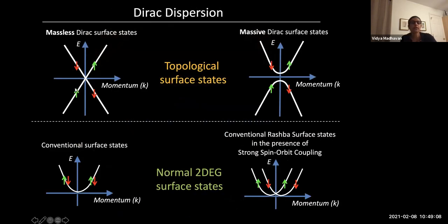So just to show you why a topological insulator is interesting, this is the band structure of the two-dimensional surface state of a topological insulator. And this is the Rashba split state that I was talking about earlier. The difference between a topological insulator and a Rashba split band is that at any given energy for a topological insulator, you have only one band crossing that energy, whereas for a Rashba system, you have these two branches that cross at any given energy. So a topological insulator has strong spin-momentum locking, just like we need, and you've gotten rid of the other band because of the topology of the bulk of the system. So this is an ideal system to realize Majorana modes.